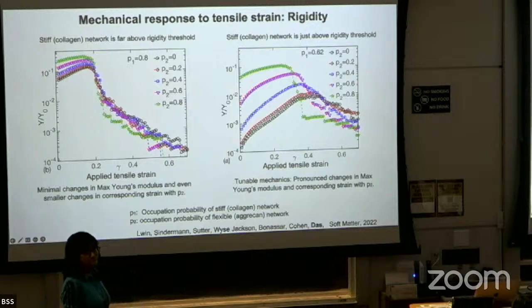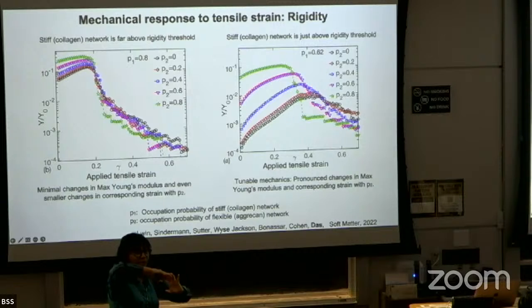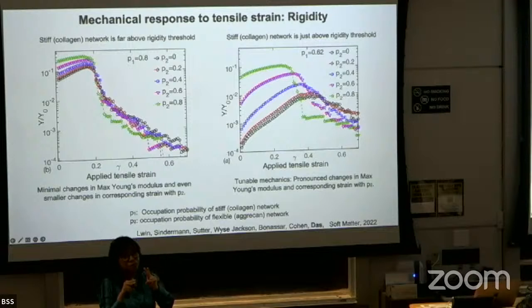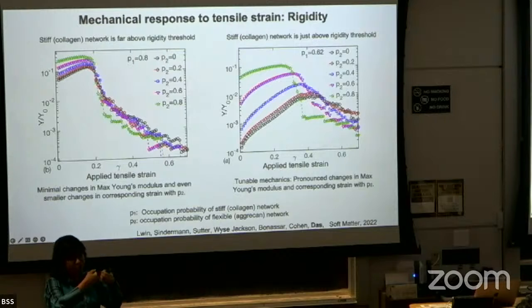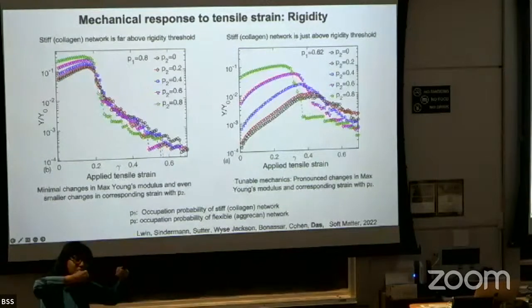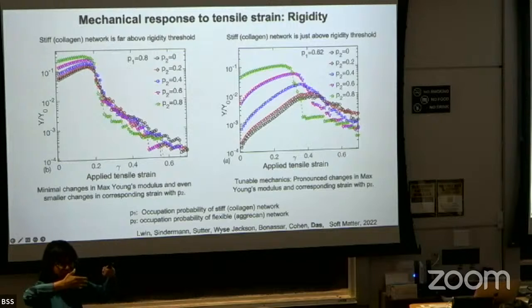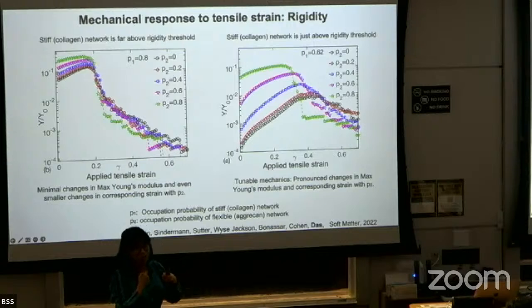Yes. Why does it get more stiff originally? That's because in a network, bonds might initially be in a situation where they are not stretched out. So I guess there are two ways stiffening can happen. First is that you're stretching your bonds across their backbones, and their overall stretching energy, or deformation energy, is increasing. So there is that. Sometimes your bonds can also be in a situation where they are not stretched out in the direction in which you're stretching. So initially, when you start to stretch, you're stretching everything along this direction, and you're also starting to align your filaments along that direction. And that can also give rise to some additional stiffening. So in a network, it could be a combination of all of those reasons.